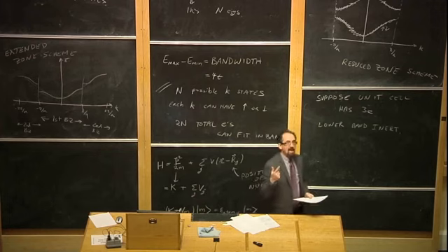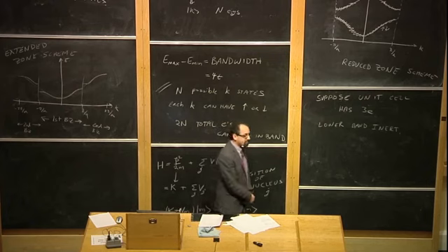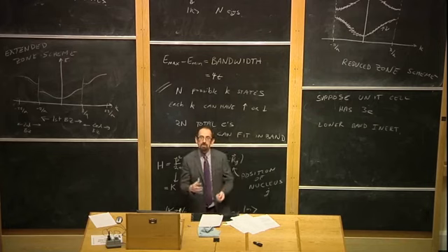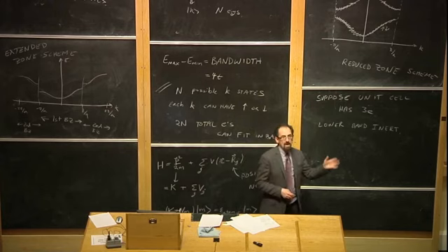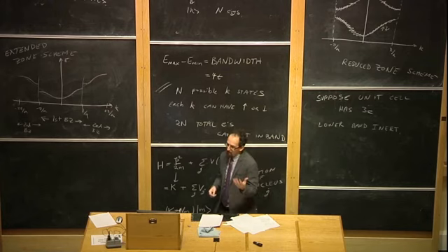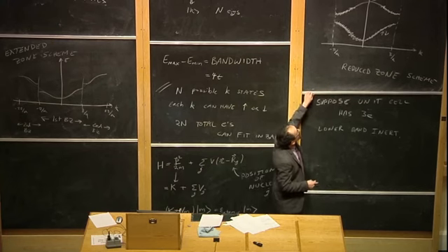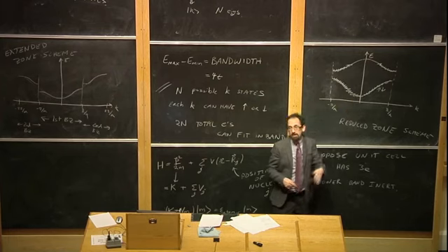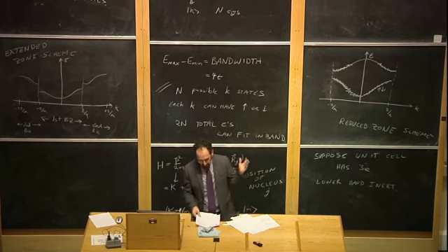But this is actually the answer to one of those puzzles that we wrote down earlier in the term. The puzzle was, why is it that you sometimes don't have to worry about core electrons? If electrons are in core orbitals, why is it you can just throw them away when you're counting electrons? For sodium, you only count 1 electron per atom and not 11 electrons per atom when you're trying to calculate the metallic density. And the reason is because basically those other electrons are completely filling bands, and the bands become inert and just aren't part of the interesting physics like heat capacity and conduction.